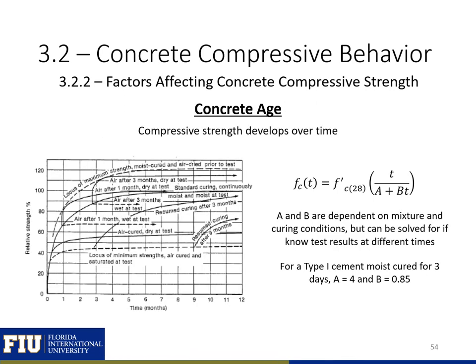The compressive strength of concrete will develop over time. A common expression used to estimate the compressive strength development over time is shown on this slide. The concrete strength f'c at any time t is equal to f'c at 28 days times t over A plus B times t. A and B are dependent on mixture and curing conditions, but can be solved for if you know the test results at different times. For a type 1 cement, moist cured for 3 days, you can assume A equal to 4 and B equal to 0.85.